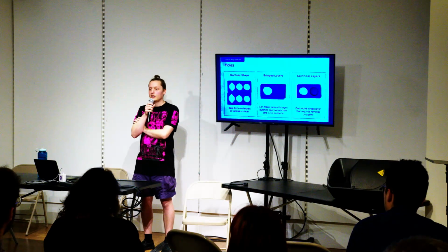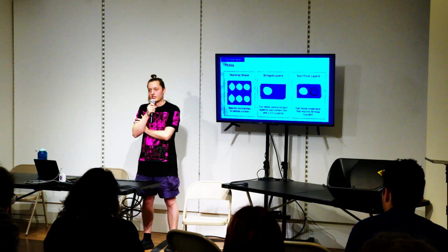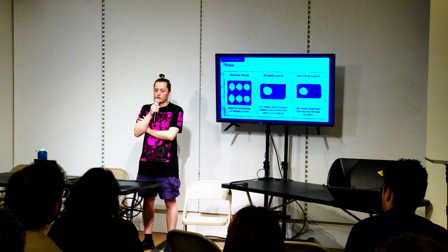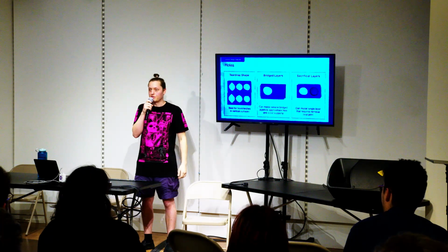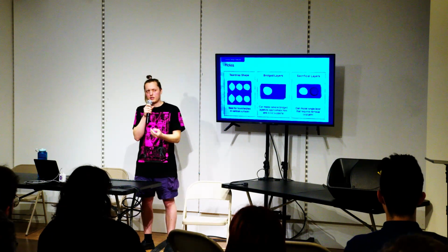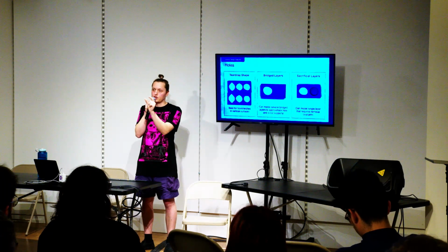So metal infused filaments are generally weaker than other filaments. I'm not entirely certain the process behind why that is, but I assume it has to do with the fact that you're sort of reducing the number of plastic chain bonds within the plastic itself by interrupting that with particles of metal. And it's usually a very fine metal powder, as opposed to carbon fiber and glass, which use chopped strands. So there's a little bit of length to them that helps add strength.